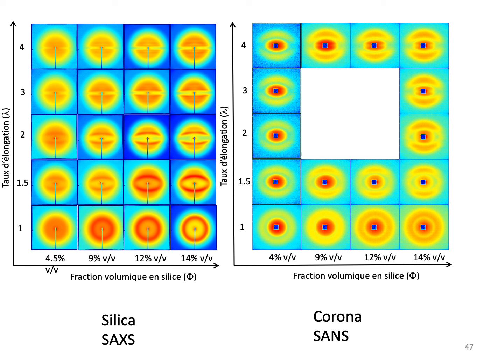You see on the left-hand side the different figures, which show some strikingly marked anisotropic patterns. And what we will do is divide the patterns on the right-hand side by the corresponding pattern on the left-hand side, so that we will get rid of the structure factor and obtain only the form factor.